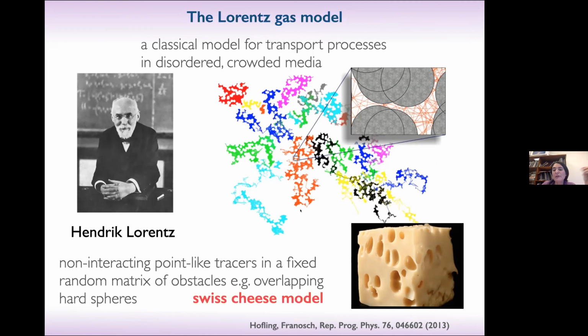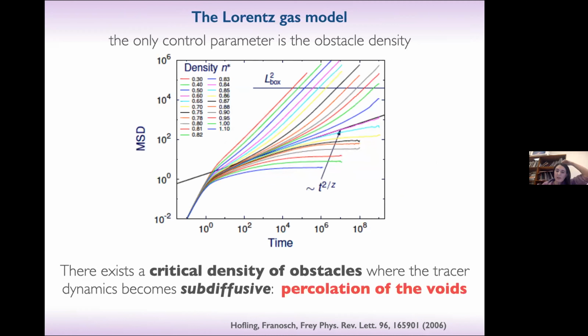And Thomas Franosch and co-workers have worked a lot on the Lorentz gas model, and they have a beautiful review article here. So the Lorentz gas model is well known because you can analytically calculate the occurrence of a transition that is related this time more to percolation, let's say, than to glassy behavior. Because in the Lorentz gas model, the only control parameter is the obstacle density. So what is the packing fraction of the immobile matrix? And then you put these point-like tracers which explore the available space, and at some point the voids in between the matrix percolate, and so the intruder, called the tracer, can go everywhere in the phase diagram and diffuse like this.